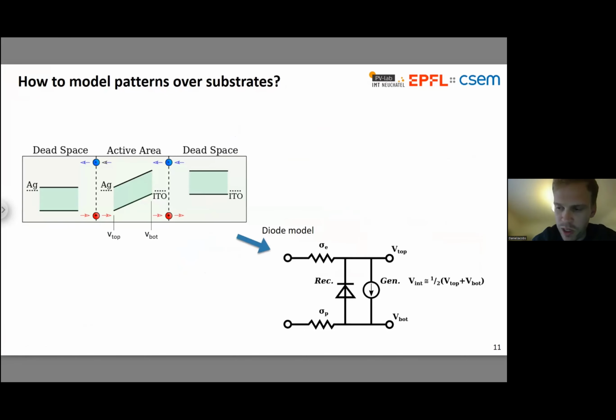So just to take this modeling a little bit further, and this is all right for a back-of-the-envelope estimate, I wanted to do a little bit better to predict the patterns of ion migration. And so essentially, I developed a class of diode models. They're basically just diode models, which use flat band type assumptions. So I just assume that my device is characterized by these two potentials at the top and the bottom of the device, which just gives me two variables to solve for.